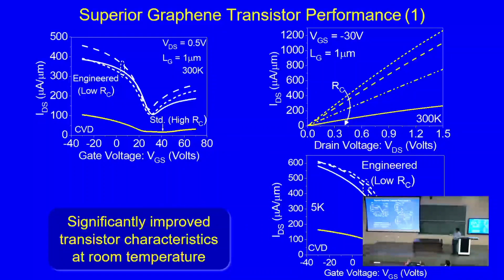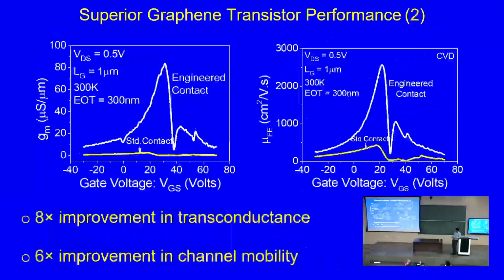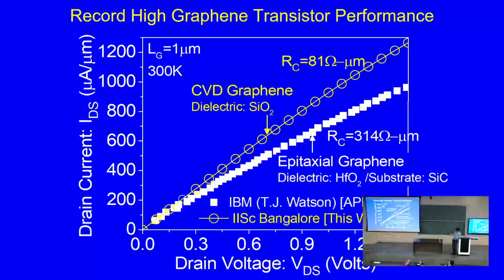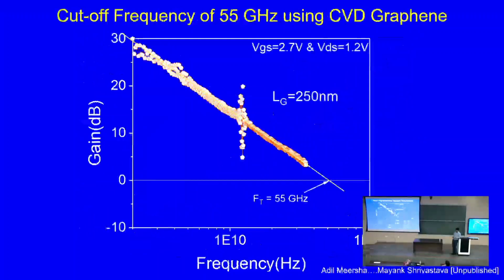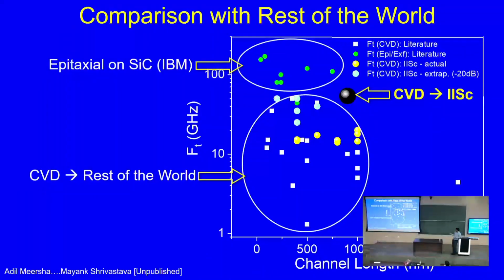So what does it mean? This is standard without contact engineering, and this is with contact engineering. You see such a nice gate control and this very nice Dirac point characteristic. So this was the comparison. This was the best reported number from IBM, and ours with the highest quality material, hafnium oxide gate stack, on silicon carbide substrate. And this is our simple process. Simple means the cheaper one: CVD graphene, silicon oxide gate stack, all measured at room temperature, is still 20% better than IBM's data. If you look into RF, we are somewhere around 55 gigahertz at 250 nanometer channel lengths, and if you compare the world, except IBM, nobody has reported these kinds of numbers with CVD graphene.